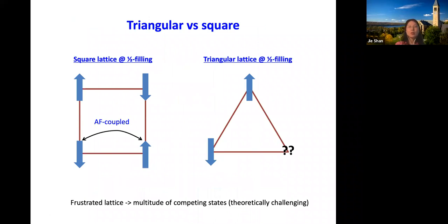We are considering a triangular lattice, and this is a little bit more complicated than, for example, a square lattice, for antiferromagnetic coupling. So we want to align this being anti-parallel. In the square lattice, it's very clear how to do it. But in the triangular lattice, if you put those two spins anti-parallel, then what are you going to do with this one? Okay. So the lattice is frustrated. You have a multitude of competing states, and this gives extra complication.